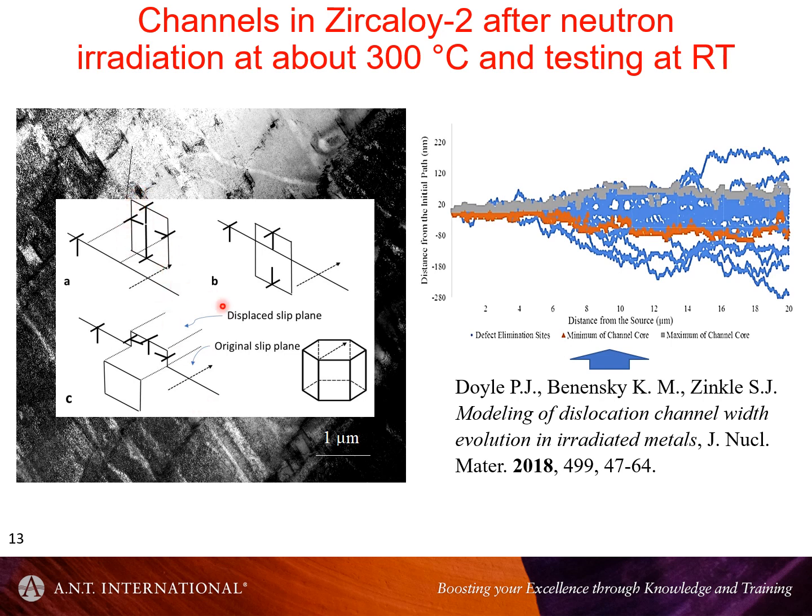You have a dislocation loop, which is like a platelet of atoms. A dislocation moves up to the platelet, and when it interacts, it will interact at some point here, and when it interacts, it sweeps up. Because by climb, in effect, it will climb. So this dislocation here will climb, in effect, by this amount over the area of the loop, and then the dislocation can continue. This is, in this example, for perfect edge dislocations.